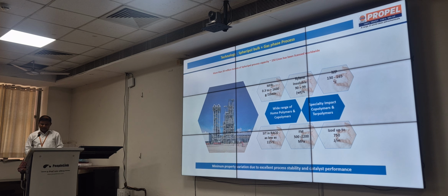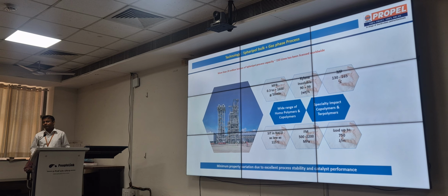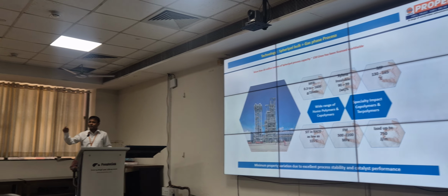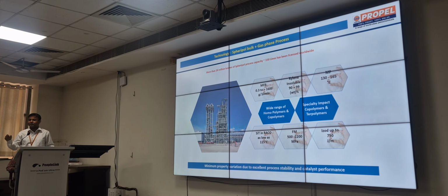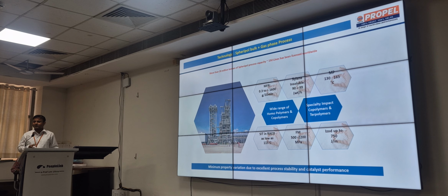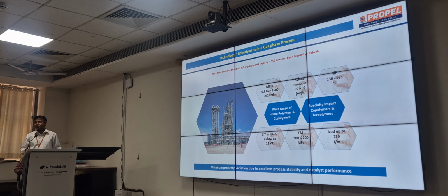Xylene insolubles are high, 90 to 99%, but that is not required. You need some atactic content also in the polymer. For applications like biaxially oriented polypropylene, you need some portion of atactic fraction also. In the raffia tape manufacturing plant, for woven sack applications, for cement packaging, you need such, because stretching is taking place. In biaxially oriented polypropylene, we are stretching the film approximately 10 times, in the machine direction as well as the transverse direction. So that's why the atactic portion is required for such applications.